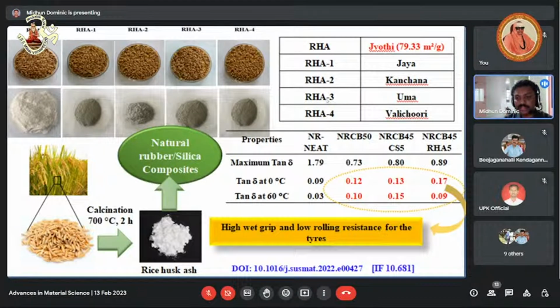NR neat represents the sample without any filler, that is, carbon black and rice husk ash. NRCB50 means natural rubber with carbon black 50 PHR, parts per 100, or 50 grams of carbon black. We also replaced 5 grams of carbon black with commercial silica. CS stands for commercial silica and RH stands for rice husk ash, 5 grams. So NRCB45 RH5 means 45 grams of carbon black and 5 grams of rice husk ash.